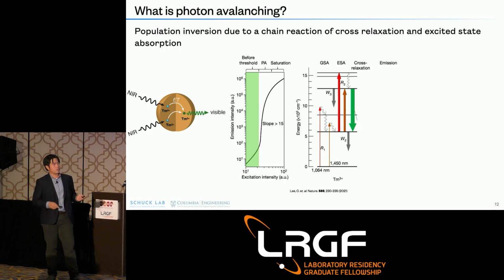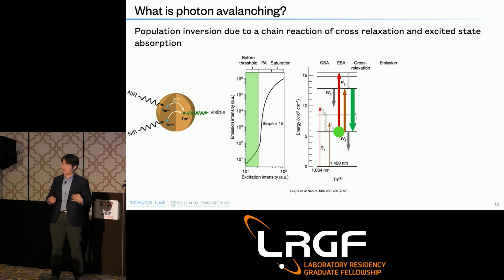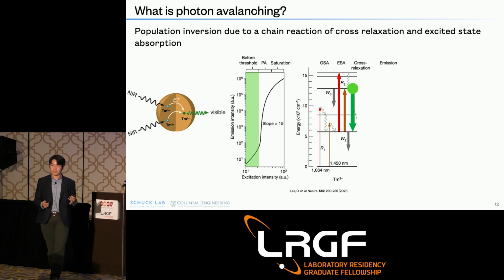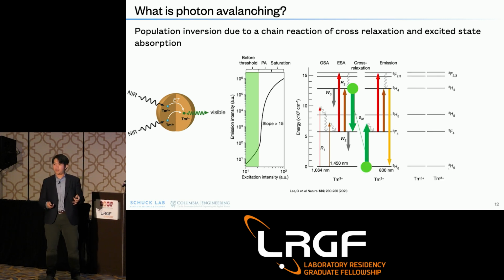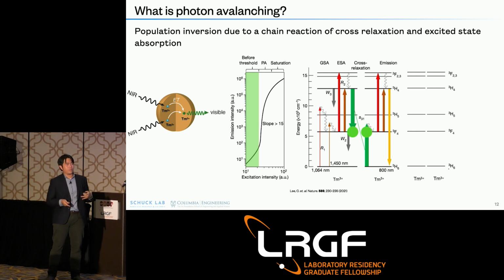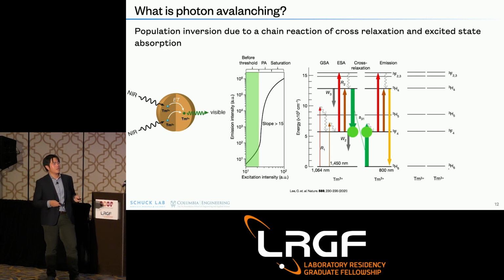But on the off chance where your material absorbs a photon, it relaxes down to the first excited state, but because the first to second excited state is very resonant and very efficient, it quickly absorbs another photon to the second excited state and sits there. But again, there's 10,000 of these around. So what happens next is you have another ion in the ground state. You can then seed the ground state into the first excited state. And here is where you can see this process go on. So two excited states seed another two ground state ions to the first excited state, and so on and so forth.